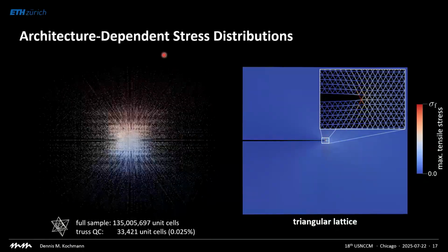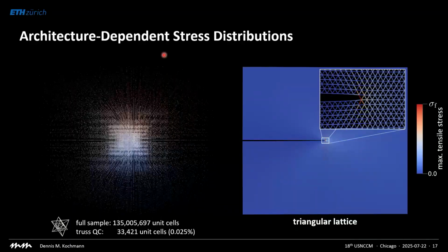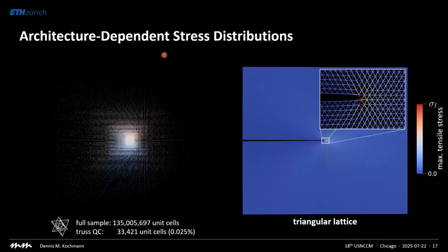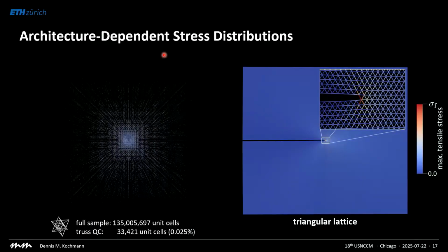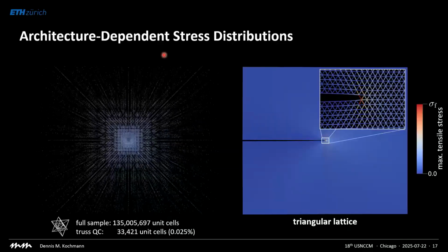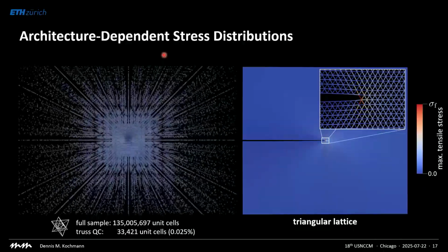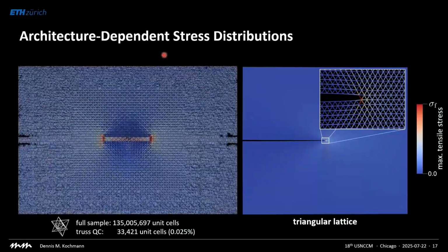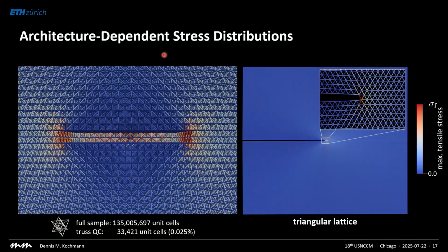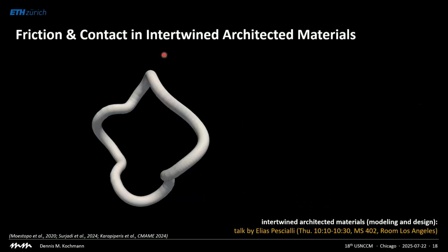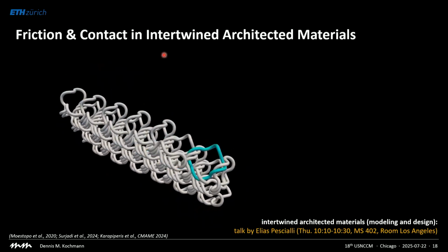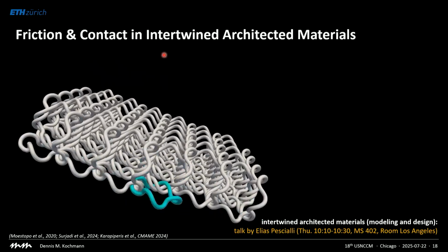Moreover, with this coarse graining, it even allows us to do this very efficiently. So you apply your loads very remotely, but you still have full resolution and the accuracy you need at the crack tip, simply by recycling the QC technique that's been around for 25 years or so. And with this, we can actually try to understand where the properties come from. We can go the forward challenge and go from structure to properties. You can do much more with this. I'll just give you one more example. Intertwined architected materials have become very popular in recent years.